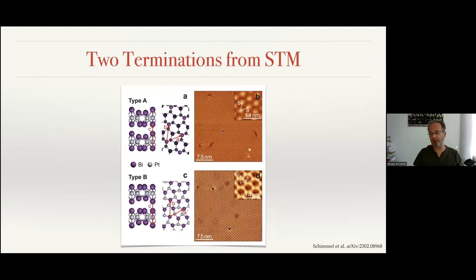The unique property of this material is that when we cleave the sample, you can always mark the particular sample surface A, and if you cleave it again and again, you will also get surface A. This is quite a unique situation, because most non-centrosymmetric materials grow with stacking faults, and depending on where you are at the surface, one could see one type of termination or the other. So this is a unique and very helpful material for experiment, because if you cleave it in vacuum, it will always be one surface or the other.